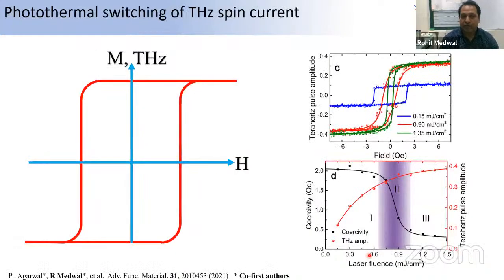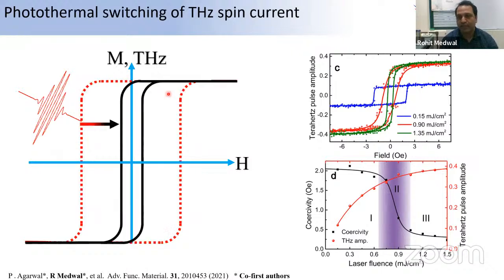What we can do is, when we shine a light on the ferromagnetic materials, we can record this hysteresis. This is the blue one, which I explained just now. If you map the electric field as a function of the magnetic field, we can map this hysteresis. When you shine the light with enough energy, you can deposit the energy on the ferromagnetic materials. As a result, you can quench the hysteresis loop. And this quenching is observed here. This is experimental evidence. We can further quench it with higher fluences, and we can see that the coercivity decreases, as well as the terahertz pulse amplitude increasing.